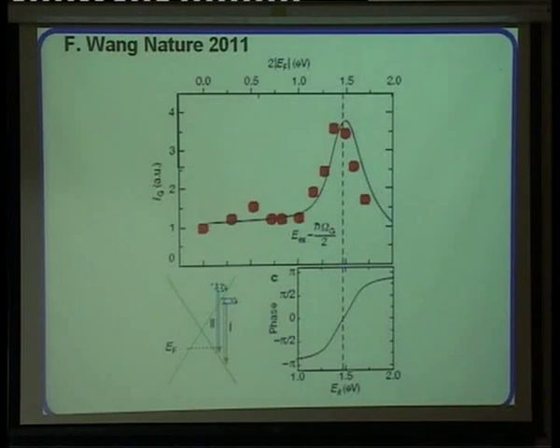In fact, the same experiment was repeated in Berkeley and published in Nature in 2011, where again they looked at the G-peak intensity as a function of doping, and at a certain doping, the G-peak was shooting up very much, and the situation is exactly what I described. It can be explained by the fact that at a certain doping, for some reason in the intrinsic sample, the processes, type 1 and type 2, cancel out, but when you change one of the processes, they don't cancel out anymore, so the intensity is much bigger than what you have only in the resonant case.